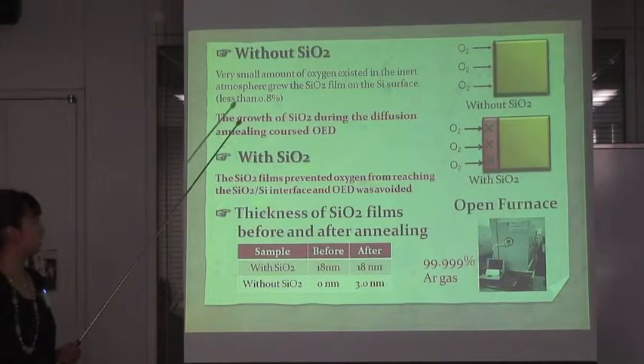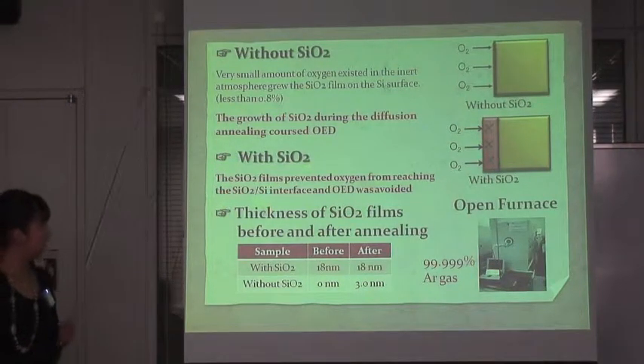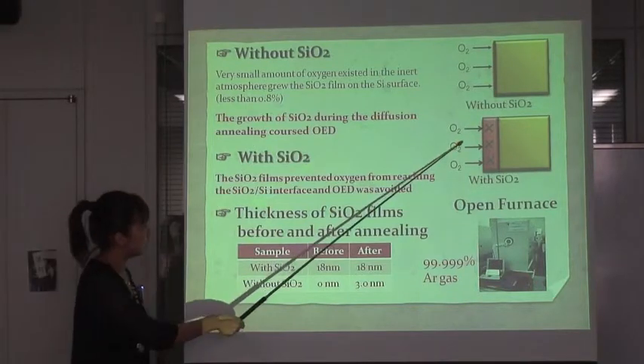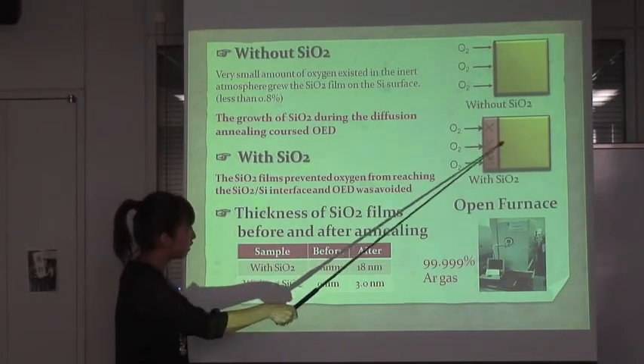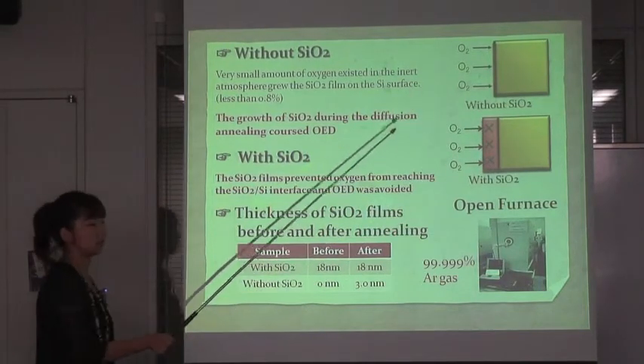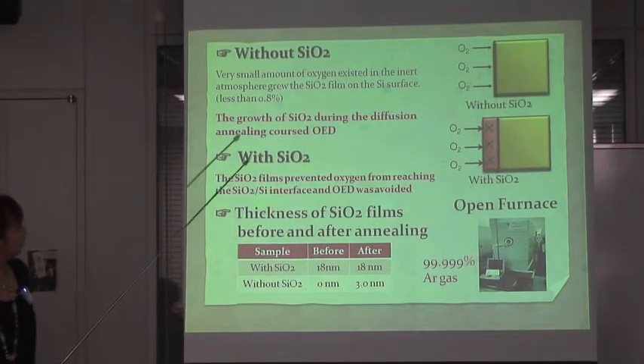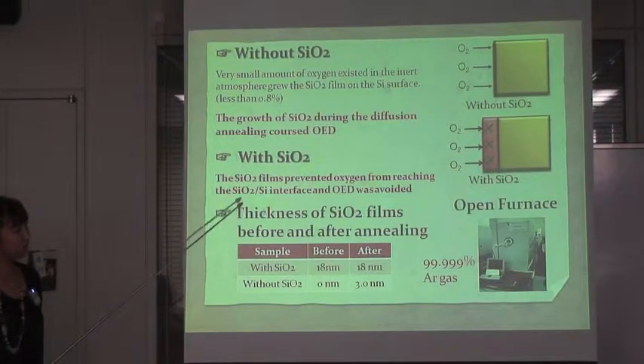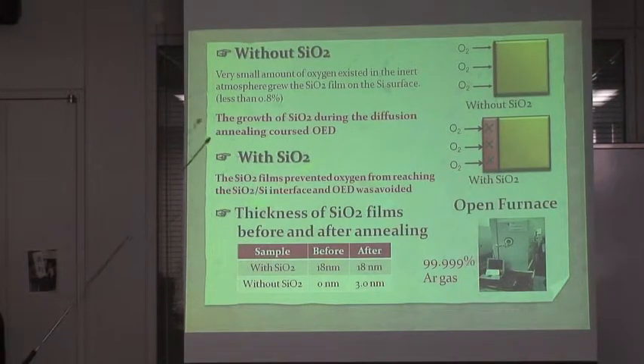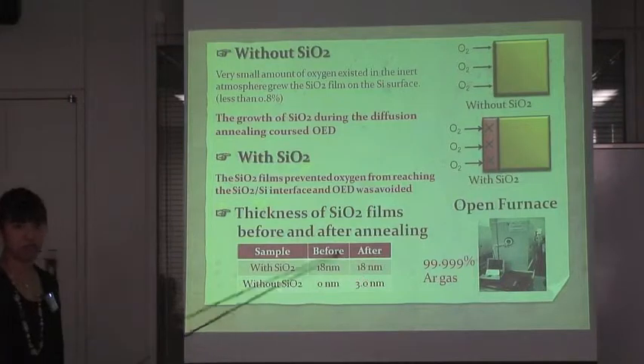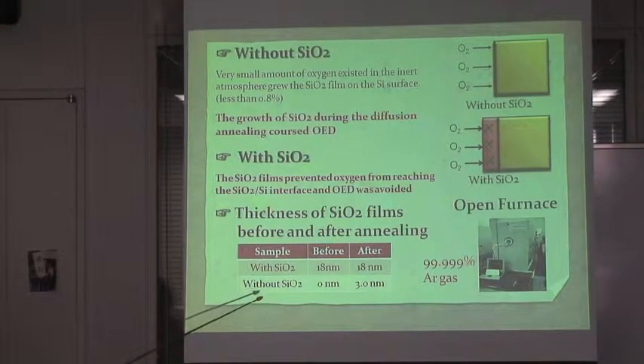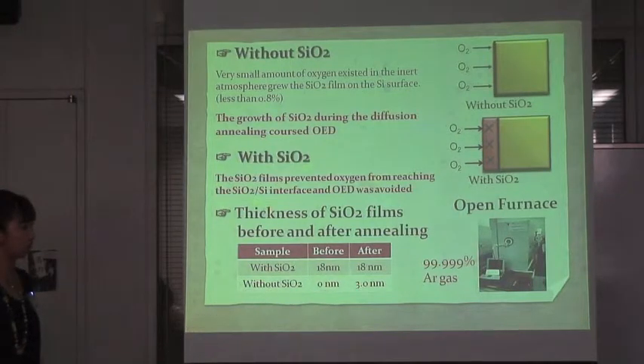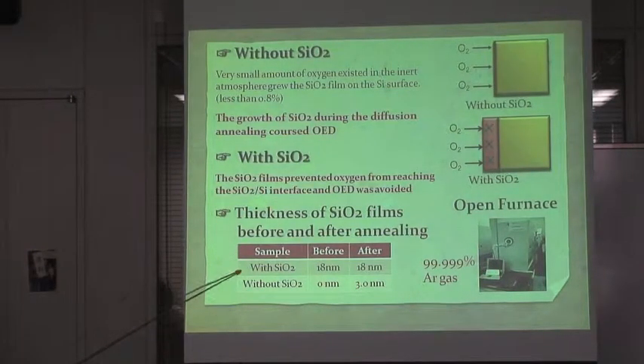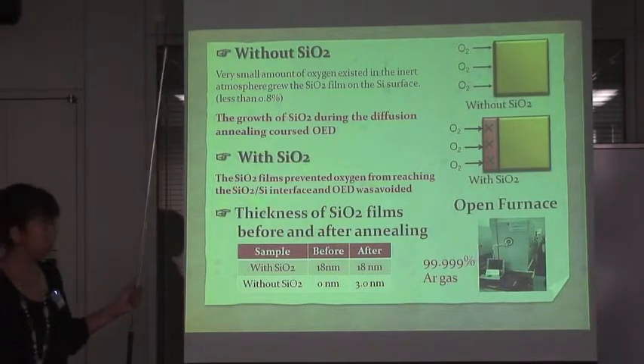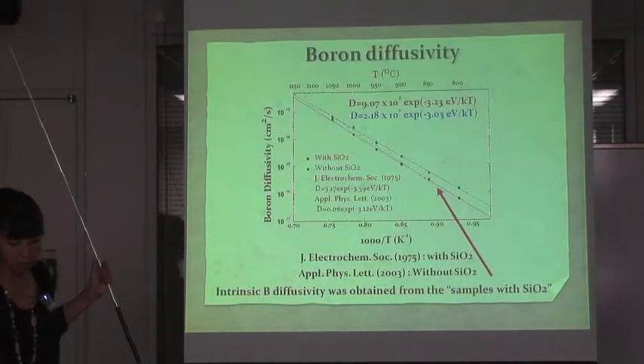On the other hand, for samples with silicon dioxide, these films prevented oxygen from reaching the interface, and oxidation enhanced diffusion was avoided. In fact, the thickness of silicon dioxide films on the samples with silicon dioxide didn't change between before and after diffusion annealing. On the other hand, we found the growth of 3 nanometer thick SiO2 on the surface of the samples without silicon dioxide. So oxidation enhanced diffusion caused the difference I showed.